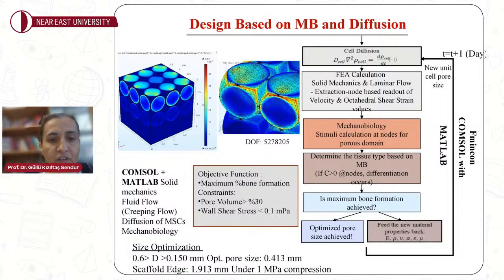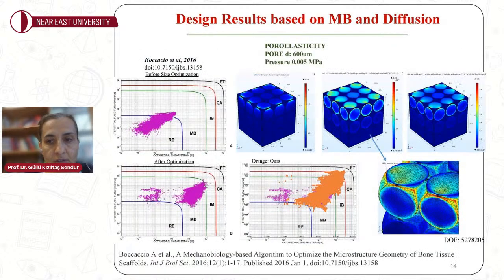We targeted maximum bone formation with certain porosity constraint and limited the wall shear stress to a value that, according to the literature, is enhancing cell attachment and is avoiding that cells would die. So effective regeneration expressed in the form of certain mathematical functions was one of the cases we were able to tackle. And this delivered us a pore size of about 410 microns.